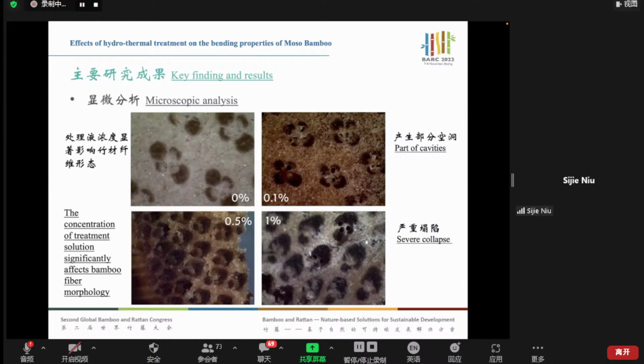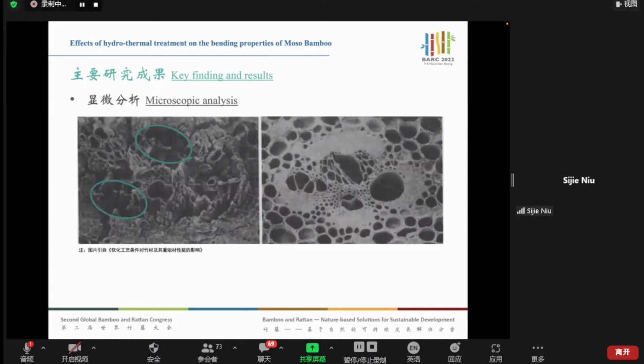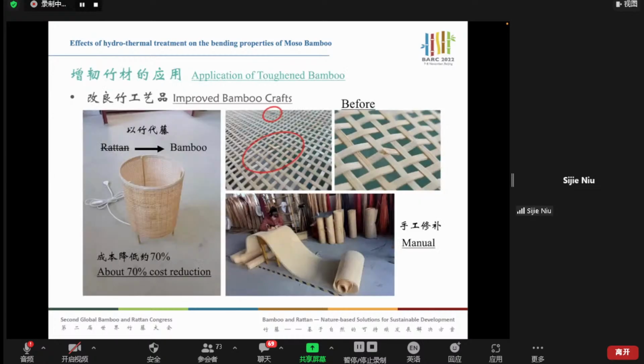Next, I want to talk about microscopic analysis. Due to different concentration percentage, you can see the bamboo fiber morphology is different. You can see the part of cavities when the concentration level is 0.1 percentage, and there is a severe collapse when the concentration level is 1 percentage. This again, you can see the vascular changes before and after treatment.